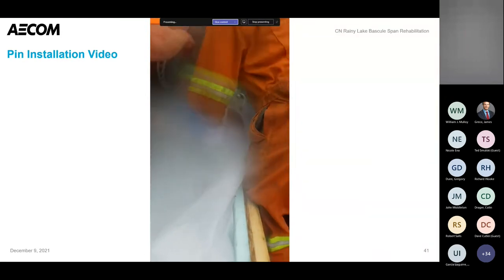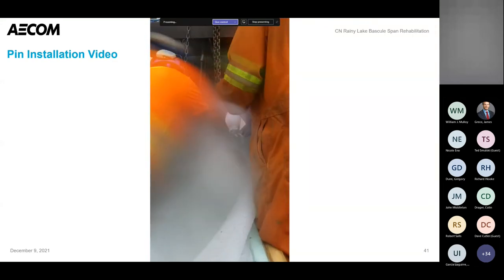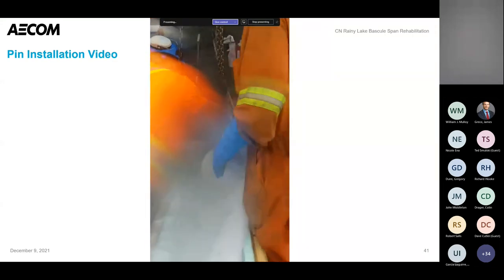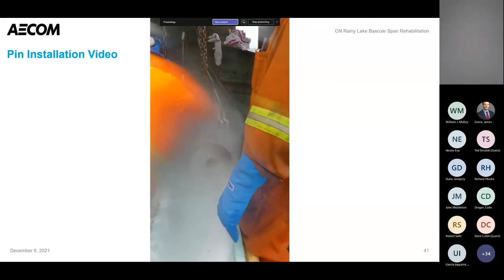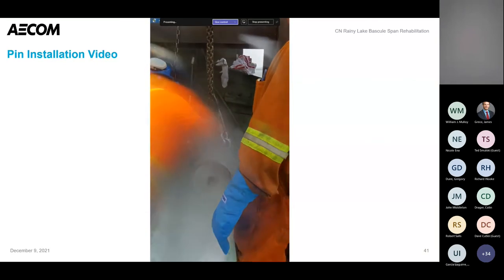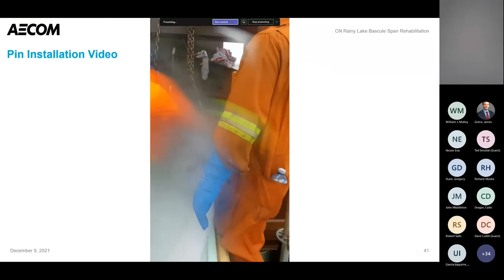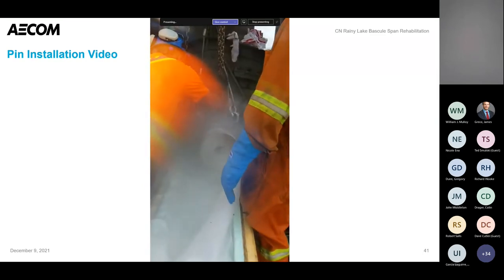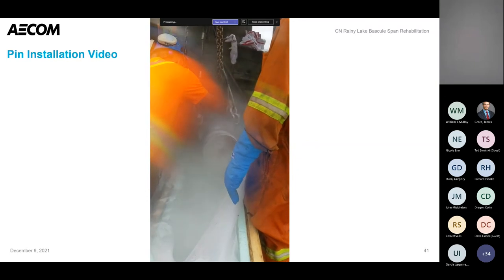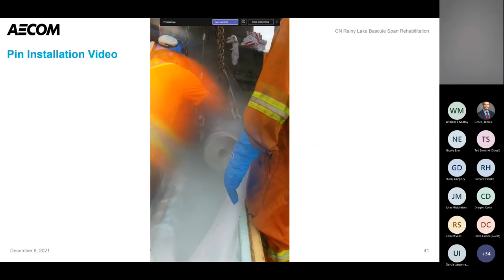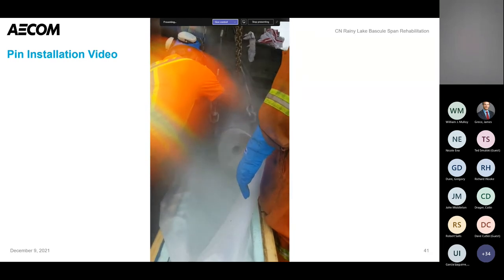Because it was raining and this is at well below freezing temperatures — dry ice is extremely cold — the rainwater was freezing on the pin and frosting up. They've got the pin out of the bath at this point, starting to heat up. There's actually a person there with a micrometer checking the diameter to make sure it's providing clearance — that it's smaller than the hole it's going into. The last thing you want is to start installing and find out it had little to no clearance and get it stuck.